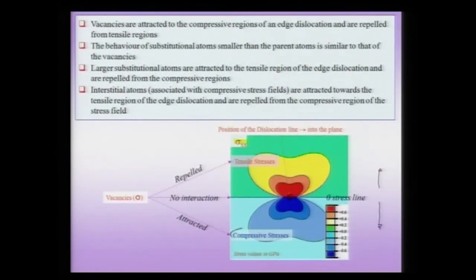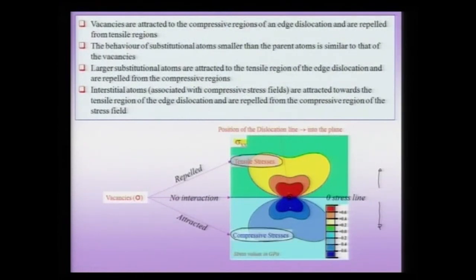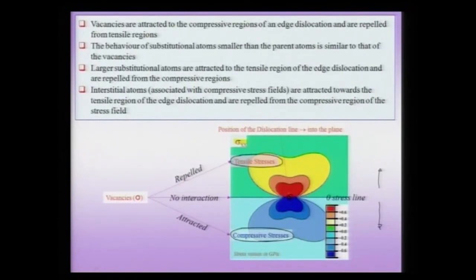The compressive stress is below and the tensile stresses are above. This complete half space being tensile or compressive is in the case of edge dislocations in an infinite medium. In a finite medium, the beautiful symmetrical picture — where the top half space is one sign and the bottom half space is the other sign — as well as the left-right symmetry, would be broken in certain other cases.